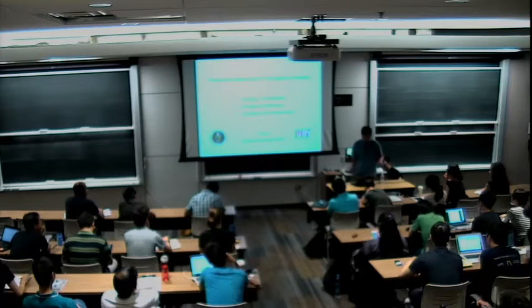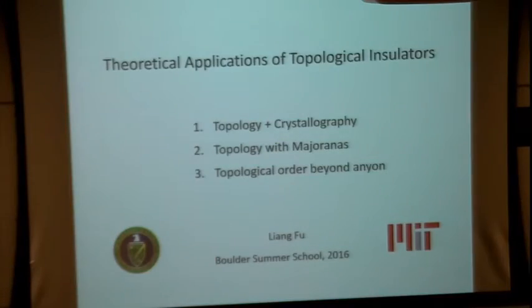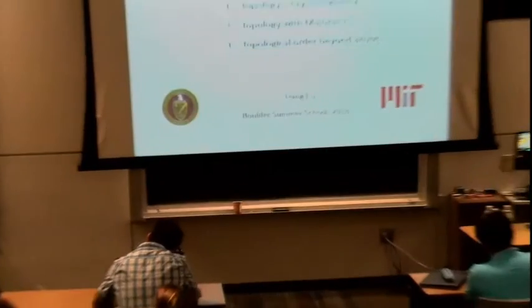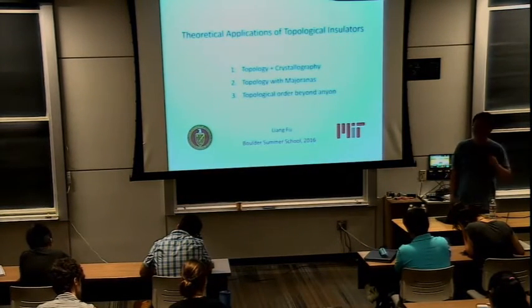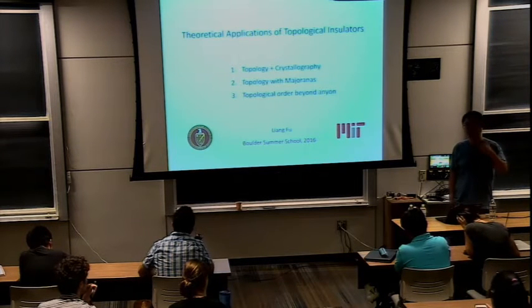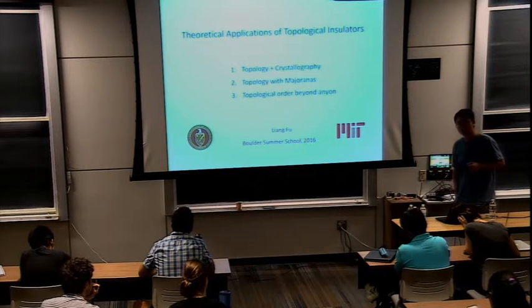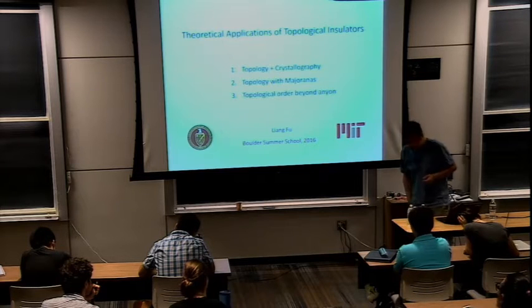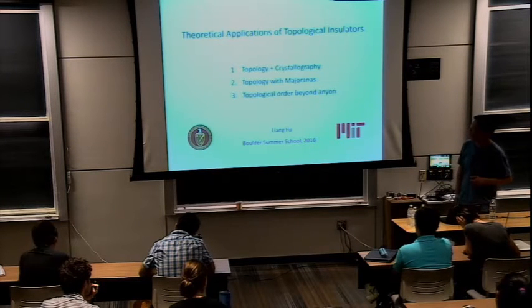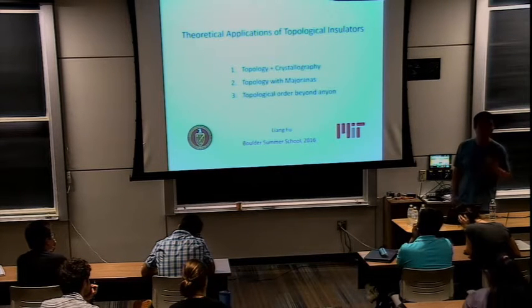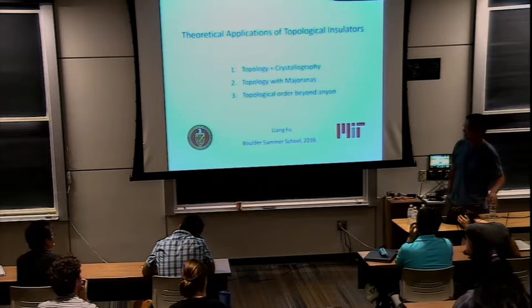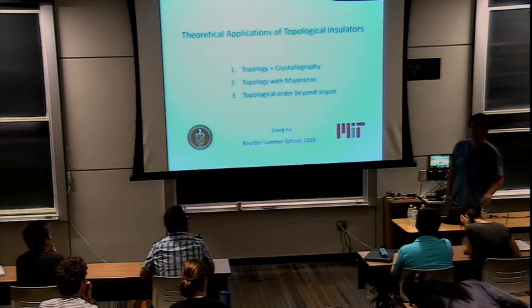And so there are many proposals that this is good for spintronics applications, basically using electron spin for information processing. And 2 years ago, there was an experiment from a Cornell group, indeed showing that once we pass a current on a thin film of topological insulators, the spin that is accumulated on the surface is strong enough that it can reverse the magnetization of a neighboring magnet, or cause the magnetization of the magnet to precess. This is something called the spin transfer torque. According to this paper published in Nature, this effect of the spin transfer torque is extremely strong in topological insulators. So there may be interesting device applications in areas of spintronics.